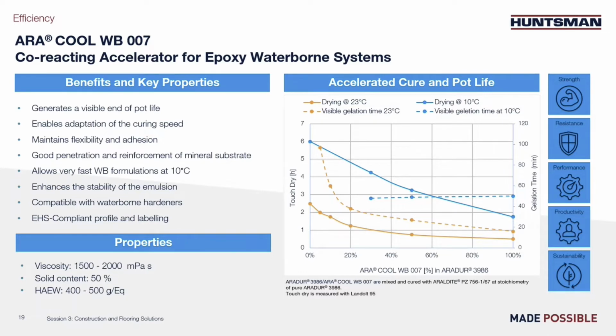At room temperature, the drying time can be divided by 5 when using 100%, but the pot life is also reduced tremendously, about 20 minutes when 100% Aracool. So, as usual, an accelerator reduces the drying time, but also reduces the pot life. And the optimization needs to be found depending on the process and the application type, let's say.